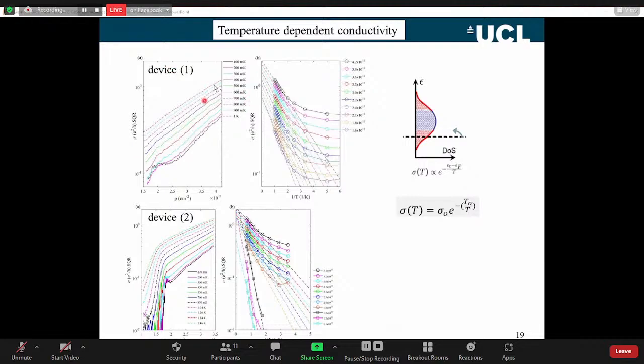If we plot now, instead of plotting the conductance versus hole density with the gate, the conductance versus 1 over T, at fixed carrier density, going from about 4 times 10^11 down to about 0.6, that's where the device goes into resistive. You can see it's thermally activated, follows a 1 over T law, an exponential 1 over T law. Interestingly enough, you can see that the intercept comes down. The intercept comes down because of activation.